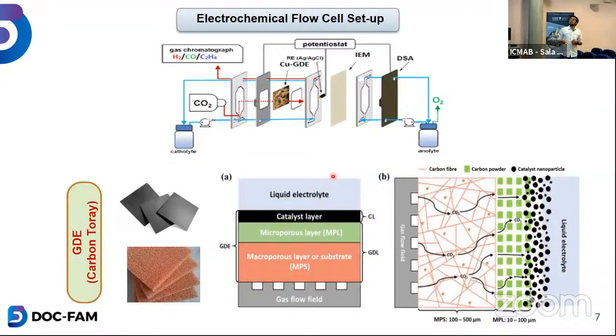So what do I do with the copper? I have this advanced form of electrochemical cell, and this is the cathode I'm working with. These are the gas diffusion electrodes that I deploy here in the cathode, the current collector. The CO2 passes from here through the catholyte, and the catholyte is also passed through a peristaltic pump. The idea is to have a gas diffusion electrode as a cathode. The gas diffusion electrode can be a scheme like this: gas flows from this side, and then it has a macroporous layer or substrate. The substrate can be a carbon paper, with or without hydrophobic treatment, or it can be a copper foam.